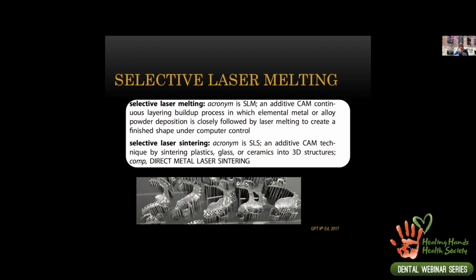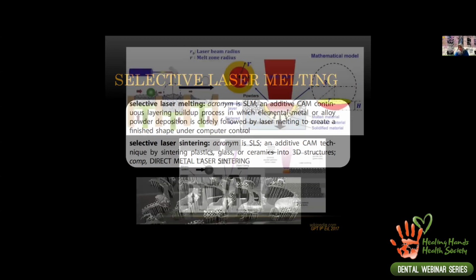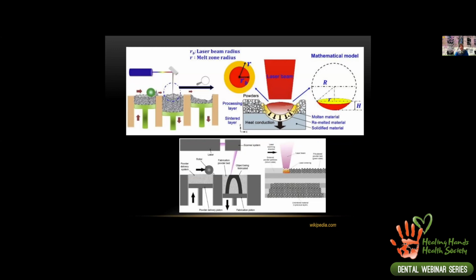And as you can see in the bottom picture, it basically emerges out of this pool of metal. Or the laser beam hits this polymer powder or metal powder, melts it just enough and fuses it together, and that's called sintering. A lot of the time, for the chrome cobalt alloy, it will be selective laser melting that's used versus sintering. Sintering is usually used for polymers that are available for some of these RPD frameworks.